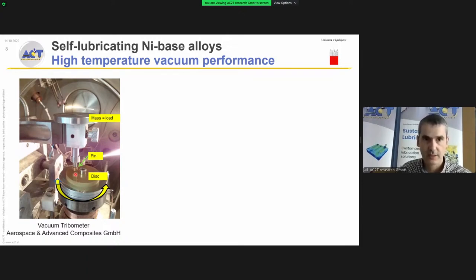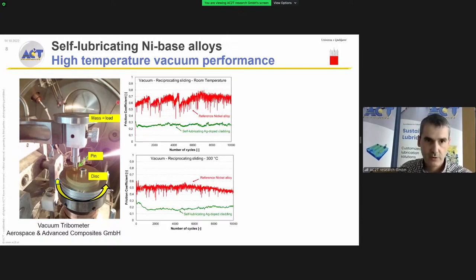So completely dry contact. And what we can observe here, the reference nickel alloy at room temperature or at 300 degrees has a really high coefficient of friction, very unsteady with these spikes that are characteristic of metal-to-metal adhesion. And when we have the nickel-based self-lubricating material, we see that friction is very low, around 0.25 at room temperature and slightly below 0.2 at 300 degrees. So again, this is metal-to-metal contact in vacuum at 300 degrees without any lubricant at all.